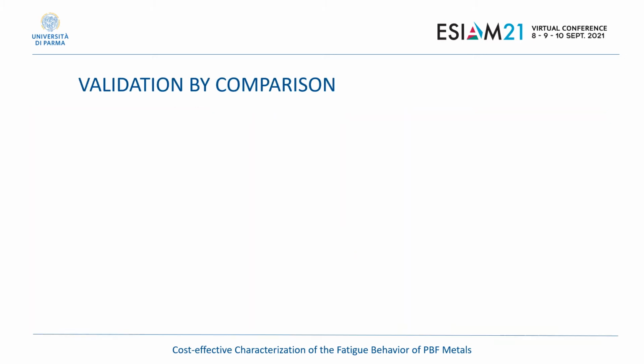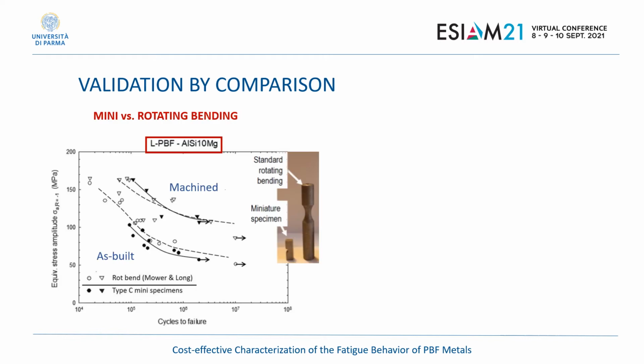We performed the validation of the methodology by comparison, considering data from the literature, as in this case for aluminum silicon 10 magnesium. The reference data was obtained by rotating bending, and combined to the reference data, we have the dark symbols that represent the mini specimen test results, both in the case of as-built surfaces and in the case of machined surfaces. You can see that the correlation among the different sets is quite good.